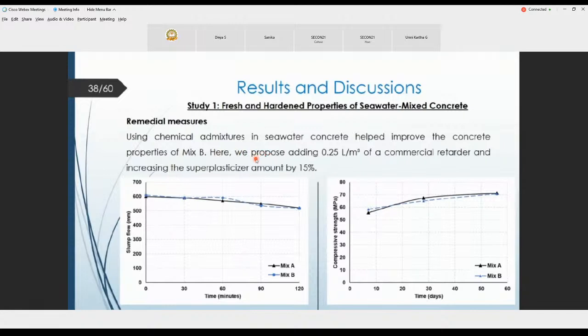Using chemical admixtures in seawater concrete helped improve the concrete properties of mix B. Here, we propose adding 0.25 liter per meter cube of a commercial retarder and increasing the superplasticizer amount by 15%. When measuring the two main characteristics that showed significant difference, slump flow and compressive strength, you can see that with the remedial measures, we have reached the same level as concrete made with natural or fresh water.